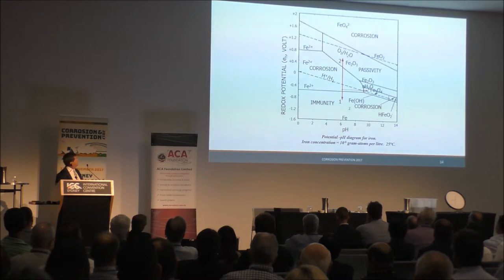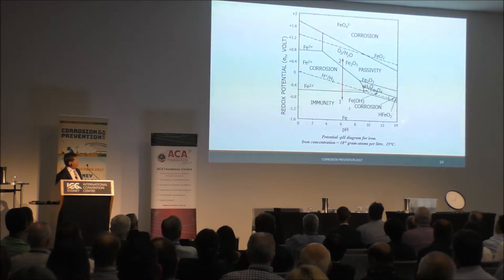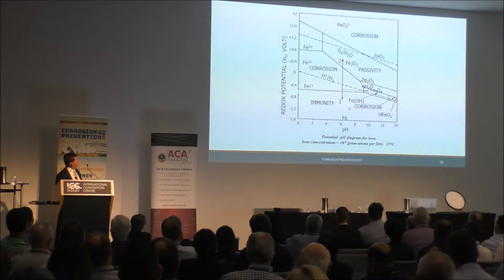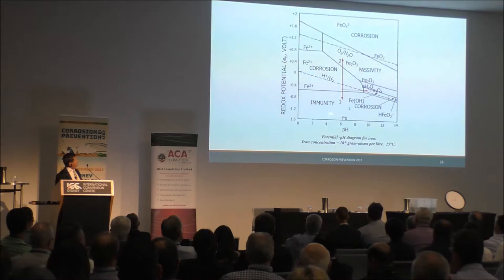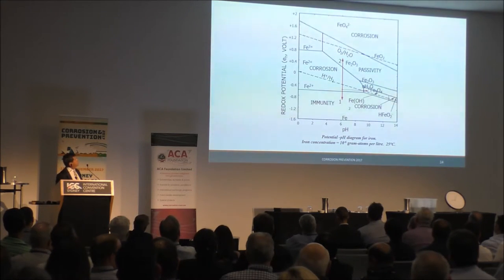So these E-pH Pourbaix diagrams plot redox potential against the pH, and here is an example for iron. It's similar to steel really, but you can see that in this spectrum of possibilities, each segment tells you what's going to happen given the redox potential at a given pH condition. So across the entire pH range, below these redox potential levels, iron is immune from corrosion in this entire box. But up here, it's in the region of corrosion. There's also passivity and even more corrosion if you go too high in the redox potential characteristics.